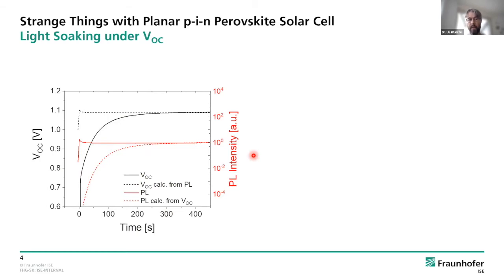The reason being that the open circuit voltage usually tells you how many charge carriers you have in your device. If you have more charge carriers, you have a higher open circuit voltage. If you have less, then you have a lower one. If you have a high charge carrier concentration, it means that you will also have a high photoluminescence intensity, because the photoluminescence which you observe with a detector, with a camera, is the product of radiative recombination, and that itself is just proportional to the product of electron and hole density.